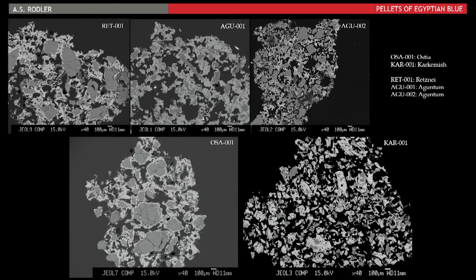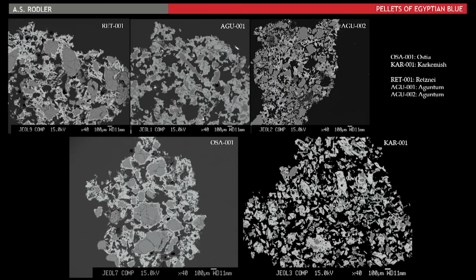So when comparing the provenance information with information about the morphology and chemical composition of Egyptian blue pellets, here, for example, with microprobe analysis for Noric examples on top, and then below are examples from Austria, and then also an Iron Age example from Karkamış in Turkey. So you can see that the Karkamış sample here is a very pure and homogeneous Egyptian blue, which is also indicated by XRD analysis. And overall, the cuprorivaite crystals of all 5 samples have a consistent stoichiometry and ratio between the calcium, copper, and silica, and the samples from Noricum and Italy are strikingly similar.